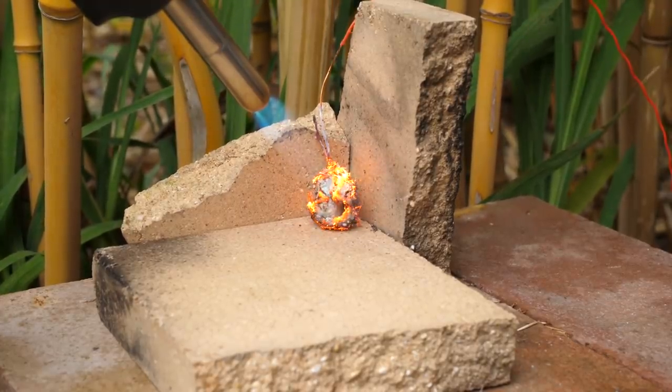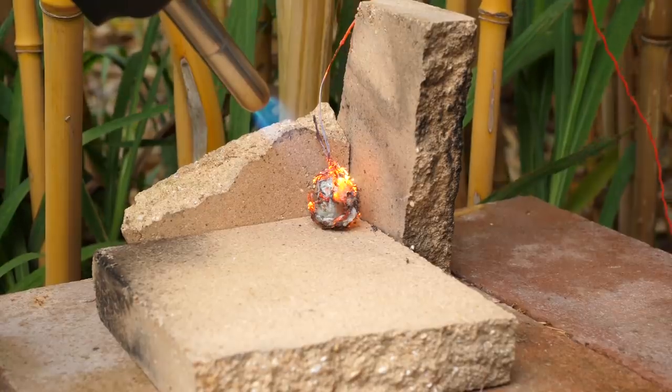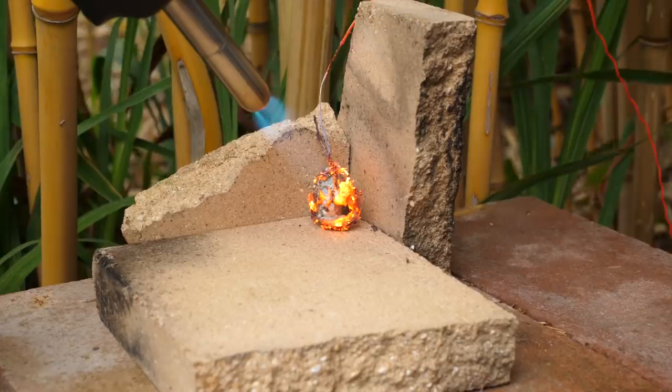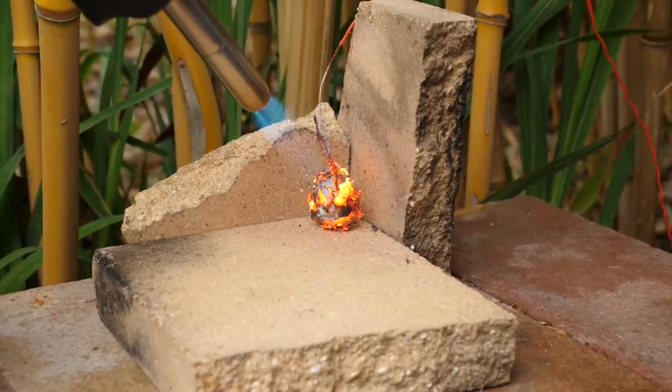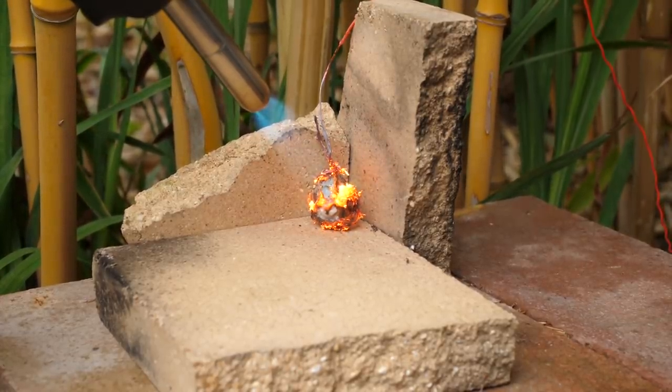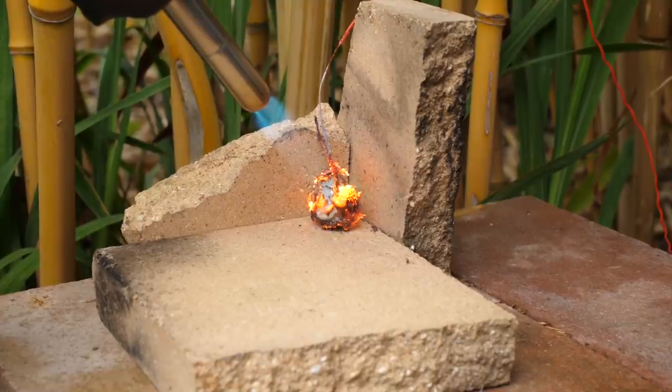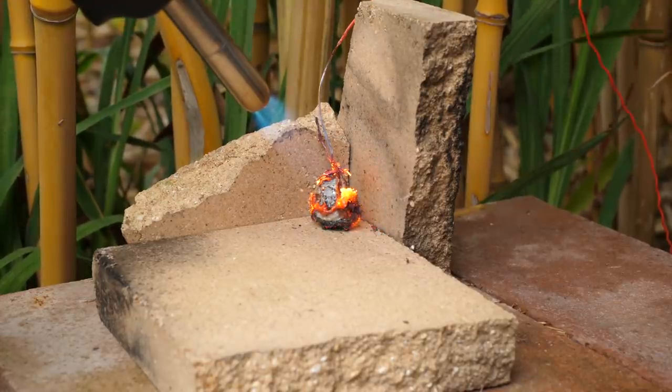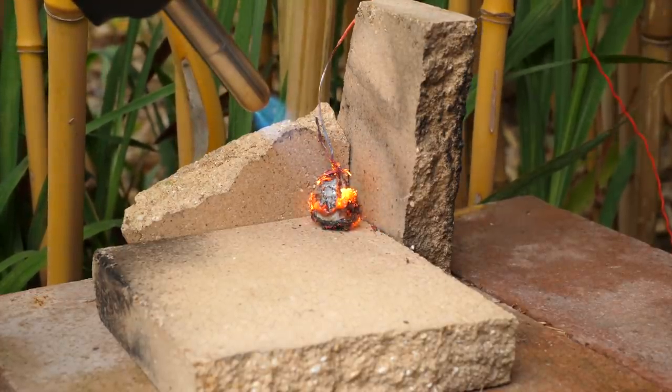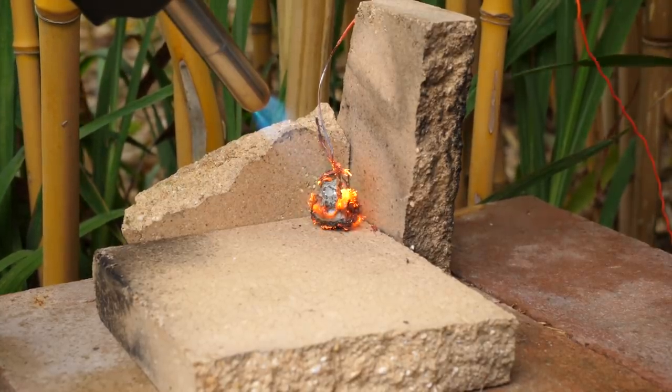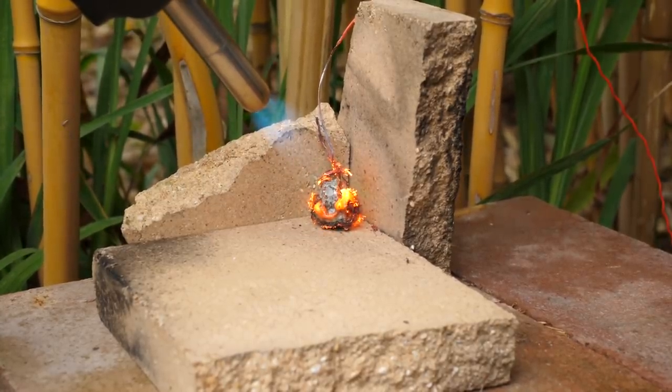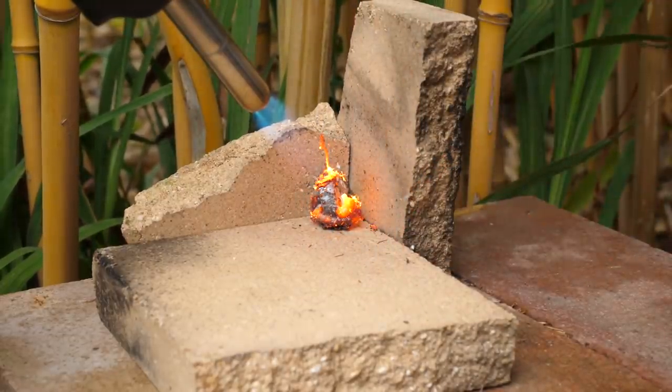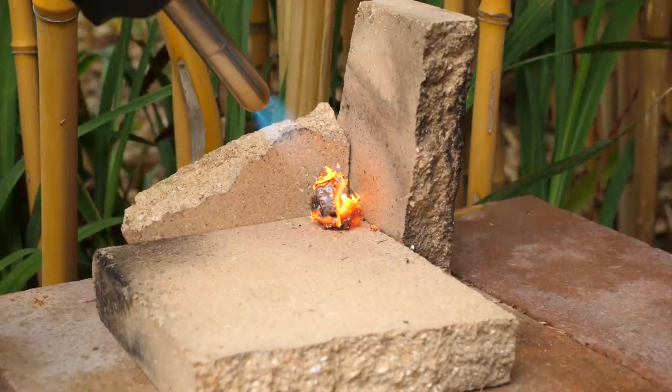The wire wool strands burn away quite quickly, but the boric acid crystals have already melted into a sticky layer which clings to the steel pretty well. It seems to work just as well as making a cage from thicker iron wire. I prefer not to use thick wire, as I'm concerned it will prevent the part from being quenched properly. The copper wire looped through the die, quite predictably melted through almost immediately.